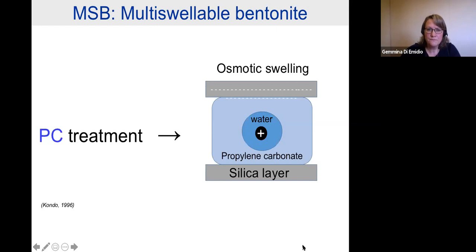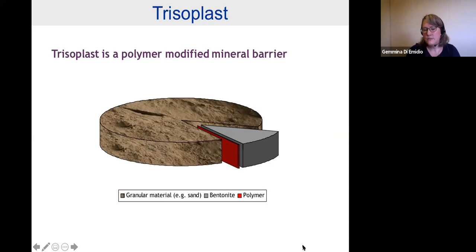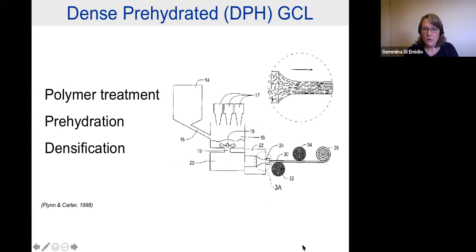Another polymerized material is Trisoplast, developed in the Netherlands. It consists of a mixture of sand, bentonite, and polymer, mixed dry — I highlight this because the treatment method matters. Trisoplast is normally used for compacted clay liners that are one meter thick, but the producers claim they can achieve a compacted clay liner of only 30 centimeters thickness, creating more volume available for waste with environmental and economic benefits. However, the dry mixing can lead to dilution of the polymer.